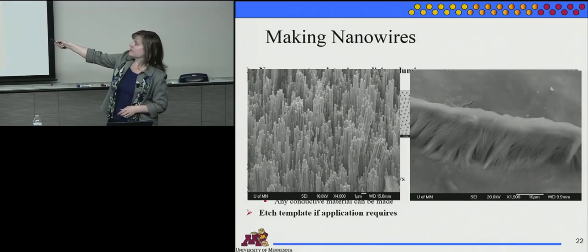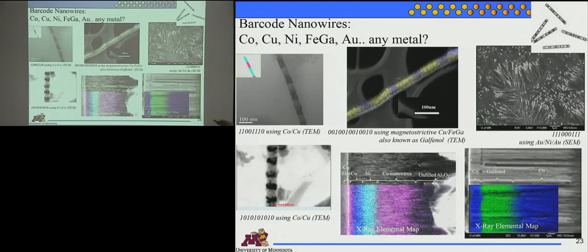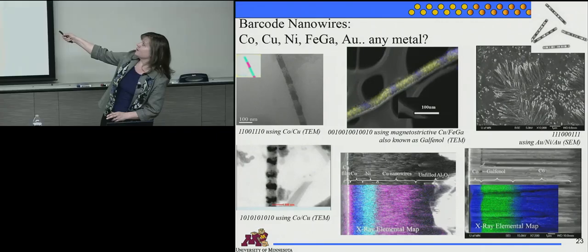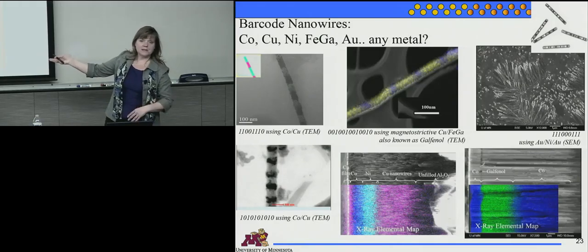And you can even see back here there's a crack, because this is the growth electrode. We didn't take the wires off the growth electrode when we etched the oxide away, which is why there's still some junk up here too. We just wanted to see what that would look like. But we can also completely free the nanowires, and then they look like this. They're also still on the growth contact, which is kind of down here. So they're spread out like a bed of seaweed.